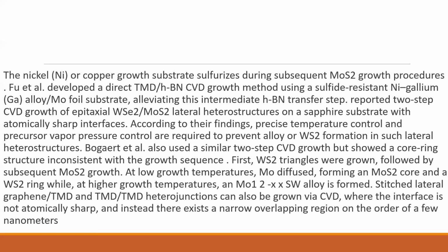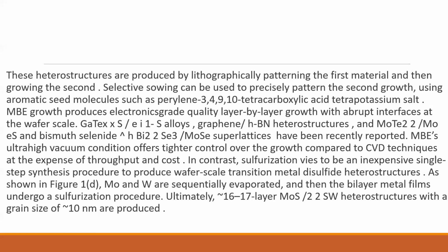At low growth temperatures, Mo diffused, forming a MoS2 core and WS2 ring, while at higher growth temperatures a Mo1-xWxS2 alloy is formed. Stitched lateral graphene and TMD heterojunctions can be grown via CVD, where the interface is not atomically sharp and instead there exists a narrow overlapping region on the order of a few nanometers. These heterostructures are produced by lithographically patterning the first material and then growing the second.